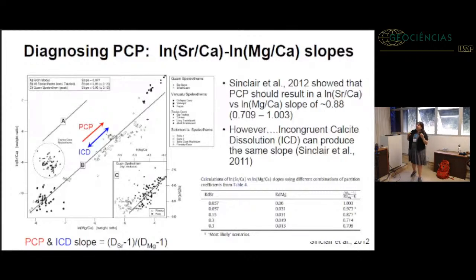That's, however, not entirely the case, because as was also pointed out by Sinclair et al. in 2011, another process called incongruent calcite dissolution can lead to that same slope. You'll also see that there's a range in slopes here, and this was based on, at the time, all the published values of D strontium and D magnesium. But they determined this 0.88 was the best.